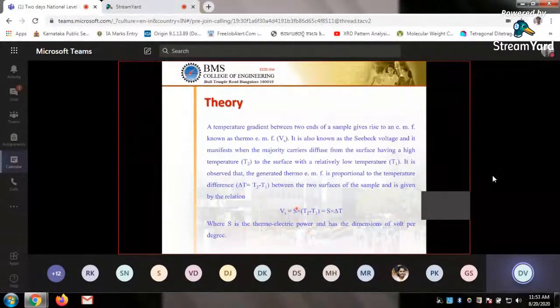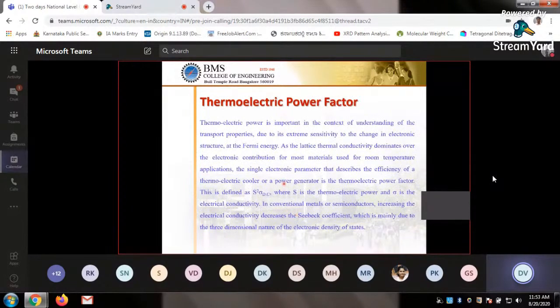How to calculate S? We know the temperature difference delta T between the upper surface and lower surface, and we can measure the thermo EMF of the sample. So by using these two values, we can calculate thermoelectric power, and you can plot a graph. We can also calculate the thermoelectric power factor. It is S square into sigma DC. You know S, make it square and then multiply with DC conductivity. You get the thermoelectric power factor.